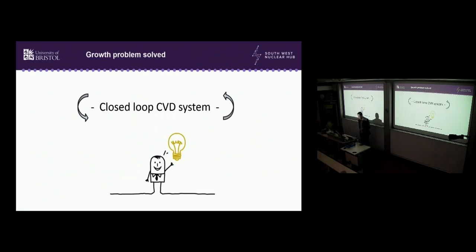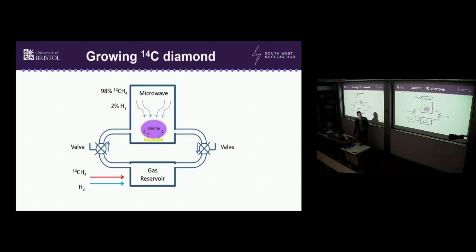And so part of the technology we've developed is something called closed loop CVD. So we close the loop so that we don't lose any gas material from the system. We essentially recycle it. And it is a very simple concept drawing because I can't show you exactly how we do it because we're patenting it at the moment. But essentially we're monitoring constantly the gas composition and making sure it's just right for diamond growth. And in doing so, whether you want to use carbon-14 methane on its own or you want to use tritium with it, you don't waste any material. You don't release anything out to the environment. And this is the technology we've been working on.